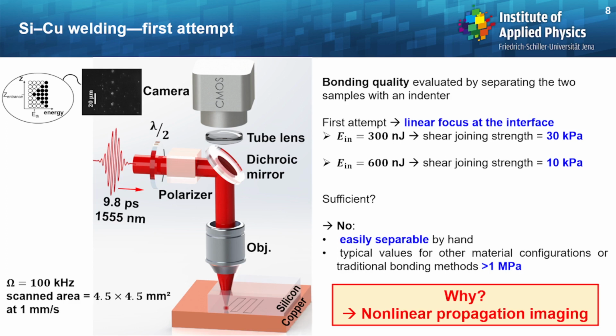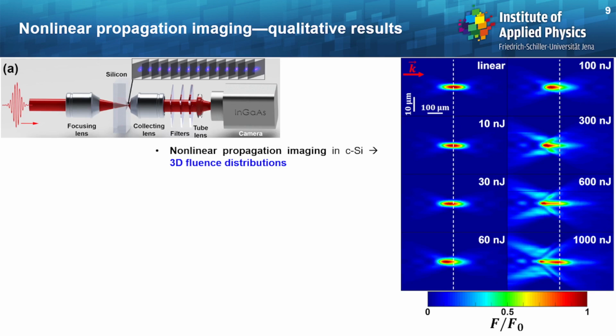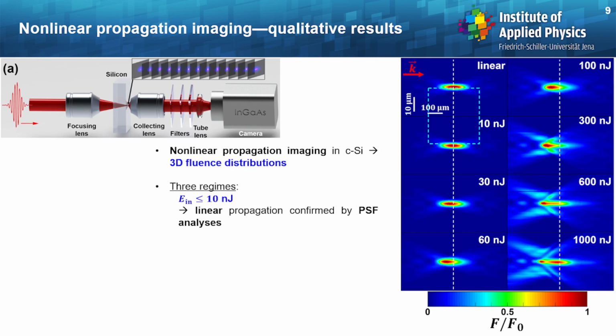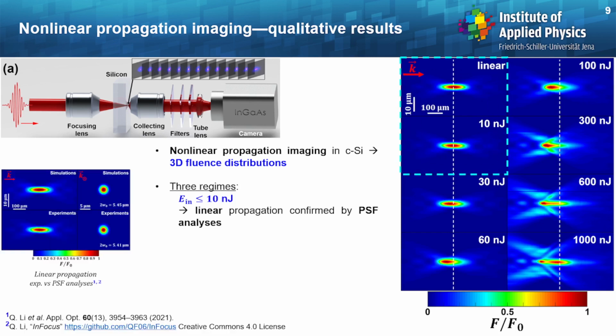In order to explain why we have such a result, we turn to nonlinear propagation imaging. And basically, we use the following setup depicted here. So we use the same objective lens as for the welding, the same silicon sample, and besides, we have a microscope, an inverted microscope actually, which allows us to record the beam shape. And then by moving the focusing lens along the optical axis, one can reconstruct the 3D fluence distributions. And these are the results you can see here on the right-hand side of this slide for different input pulse energies. So on those results, one may distinguish three different regimes.